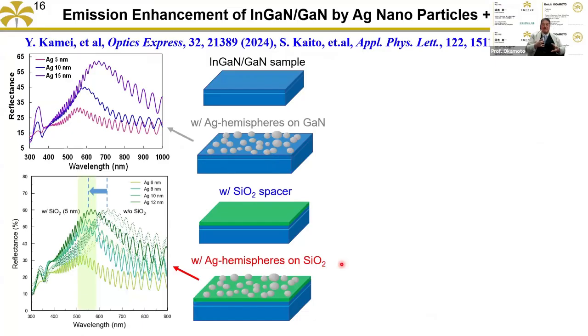But recently we found a good way. If you put the silver nanoparticle directly on the gallium nitride, the refractive index of the gallium nitride is very high, 2.5. That's why the resonance peak becomes shifted later. That's one problem. Another problem is that after 1 or 2 days, the metal nanoparticle was destroyed. So the metal nanoparticle is very unstable on the gallium nitride.